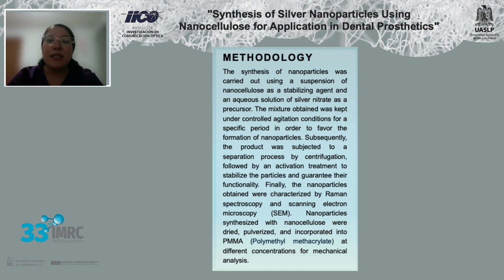The synthesized nanoparticles were characterized by, first, Raman spectroscopy, which allowed the identification of characteristic vibrations of the nanocellulose, and changes associated with its interaction with the nanoparticles. And the second is the scanning electron microscope, which allowed the observation of morphology and distribution of the nanoparticles.